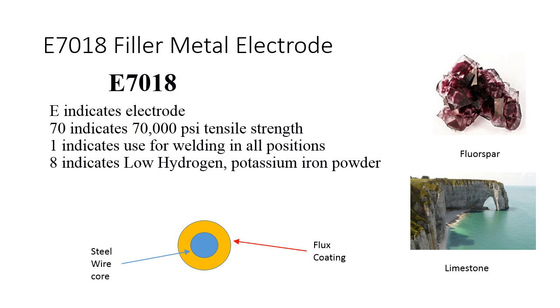7018 filler metal electrode. 7018, once again, like with 6010, the E indicates electrode. The next two digits indicate that it's got a tensile strength of 70,000 PSI. The third number in there, 1, indicates that it is welding all positions. Then we get to the 8. This indicates the kind of flux coating we have. So in this case, it would be a low hydrogen potassium iron powder electrode. And from what I've been reading, the majority of that material is made up of fluorspar and limestone. And then they throw in iron powder and some potassium. It's basically a mineral coating, from what I've read.